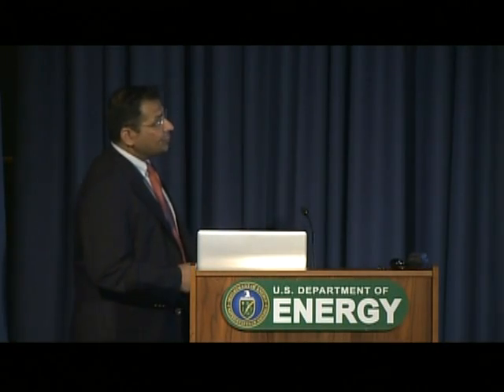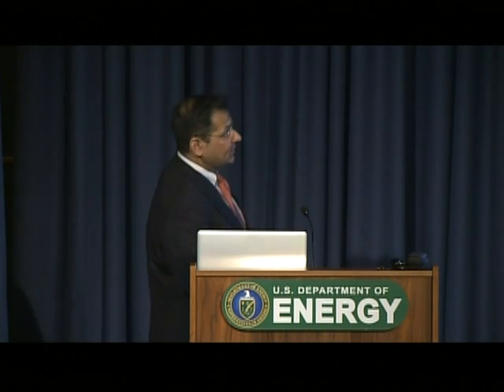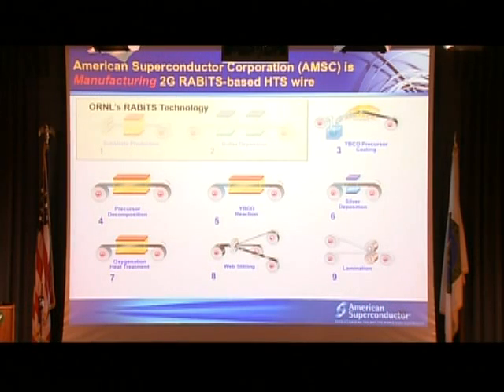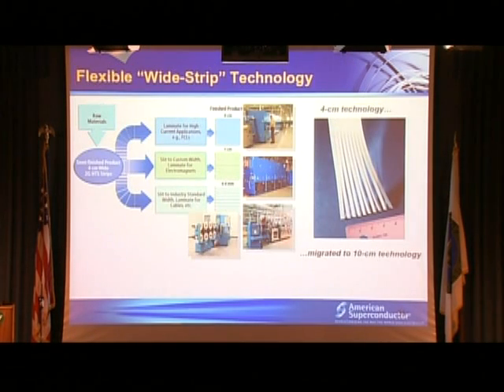As I mentioned, American Superconductor, currently the world's largest high-temperature superconductor company, has licensed this technology from Oak Ridge. After they deposit the buffer layers, they dip this into a chemical solution to deposit the superconductor. They heat treat in a furnace, and they form a nice single crystal-like superconductor. They deposit a contact layer, and then they mechanically slit. And what I mean by that is they make a wide tape of the superconductor and then mechanically slit the tape into the right width for the application in question. And this is just glimpses of their factory that they have in Devens, Massachusetts.